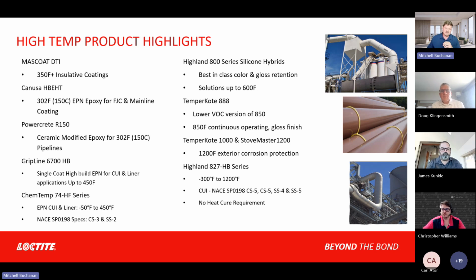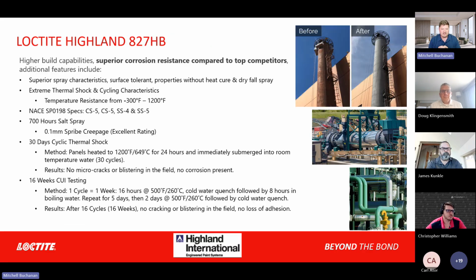And then we get into the highlight of the day, which is going to be our Loctite 827 HB. So negative 300 to 1200 Fahrenheit, excursions up to 1500 Fahrenheit, meets various SP0198 CUI specs. And we have lots of testing on this product for scribe creep and salt spray, thermal shock resistance, CUI testing, very heavily used on continuous operating equipment, like the firing drums at asphalt plants, exhaust stacks, and then CUI applications where you are insulating this equipment for energy retention, but it's still running very, very hot. And so you have to protect against CUI.